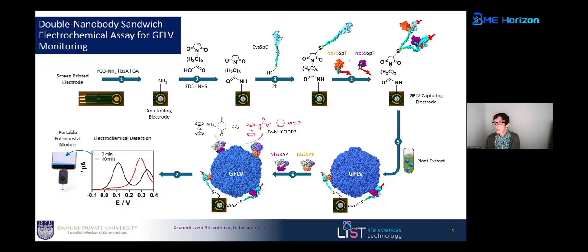Using these small synthetic bioreceptors has several advantages. First, they make the assay cheaper in general, but the small size of the bioreceptor also helps in getting better electrochemical signals because we have fewer diffusion barriers than we would have with these around 15 nanometer high antibodies. So if we get them to the surface and then we use a plant extract, so you take a plant, you grind it, and then you throw it on the electrode. In the presence of a virus, we will therefore have attachment to the surface.